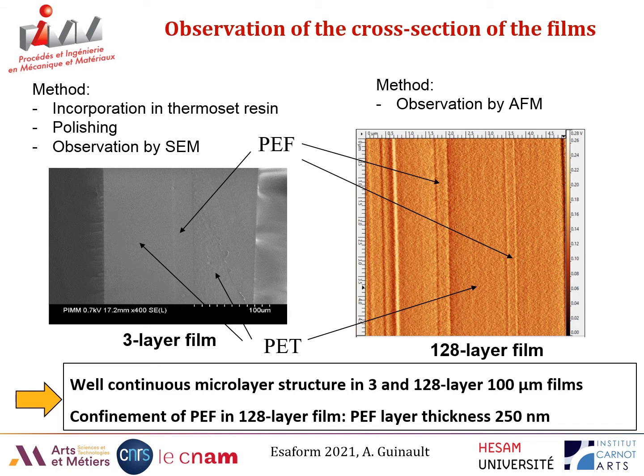So we have observed a well-continuous microlayer structure in 3 and 128-layer 100 micrometer films, and finally a confinement of PEF at a thickness of around 250 nanometers, measured on this figure at the right, compared to the 230 nanometers weighted by the calculation. So it's good.